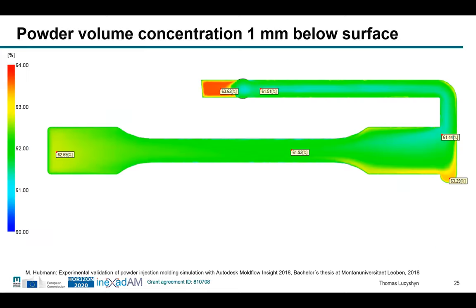Another result is the powder volume concentration 1 millimeter below the surface. So we look onto the part. So the melt is coming into here. There's the gate location, it comes in here, then it flows here a little bit, and then most of the flow goes in this direction, filling the whole specimen. And what we see here are the results, the volume percentage from the prediction of the simulation. In this area, we have some higher concentration of like 63 or 64% almost. Here, it's a lower concentration. Again, here in this stagnation zone, we see some higher concentration.